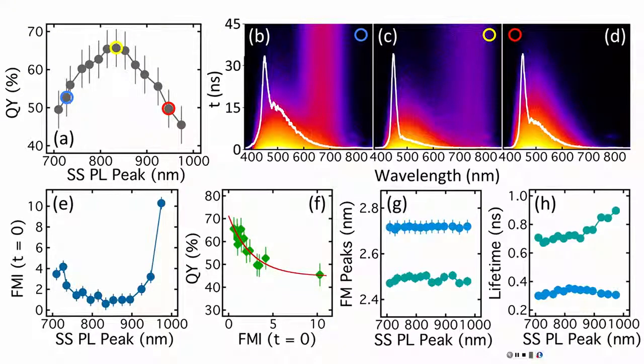So here's the first test. If it was really direct, call this transition 1 and this transition 2, how could this one be affected by quantum confinement but not this one? Both should be affected, otherwise it doesn't make sense. Are you sure about that? Of course, because the whole band is affected by the confinement effect.